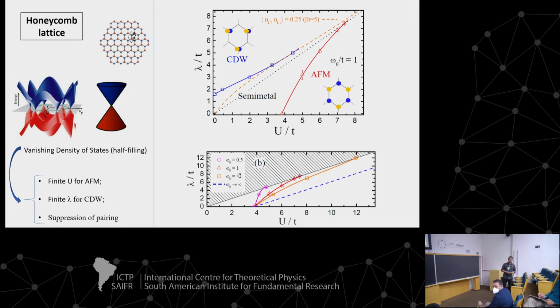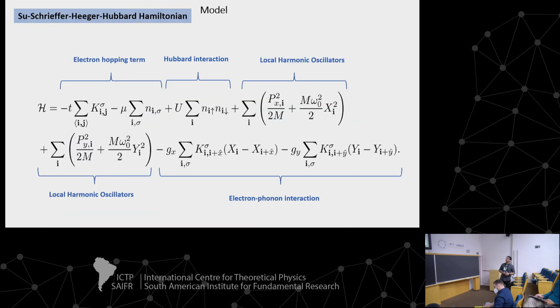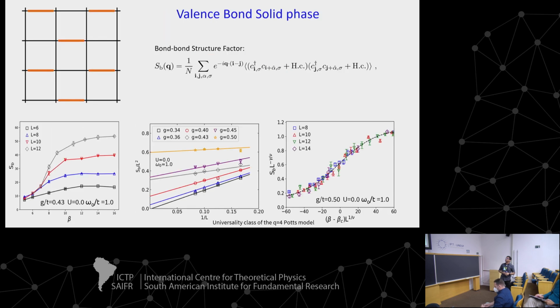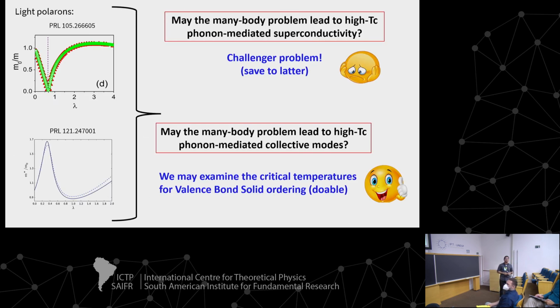So you mentioned that the problem with increasing TC by increasing the electron-phonon interaction is the fact that the mass increases. I'm old enough to have learned from the old masters that the problem usually is that there is a structural transition before you can increase TC. In other words, you have valence bond solids here. So I think the question is whether you can increase TC before you go CDW. And yes, I think that's the real problem that you face trying to increase TC by increasing the electron-phonon interaction.